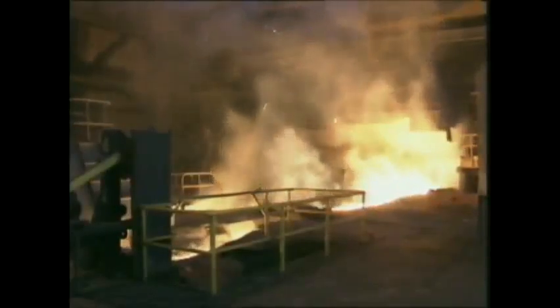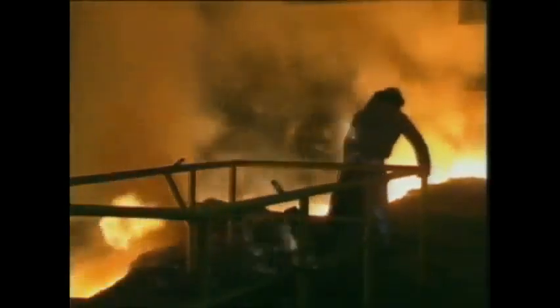The air is preheated to around 1250 degrees centigrade in hot blast stoves and blown into the furnace through tuyeres, which are equally distributed around the furnace. Moving downwards, the sinter, coke, and limestone are converted into liquid iron and slag. To save the use of the more expensive metallurgical coke, sometimes pulverized coal or oil is injected. By computers, the process operating parameters are kept under close control. The iron, termed pig iron, is collected at the bottom of the blast furnace and tapped into a torpedo ladle.